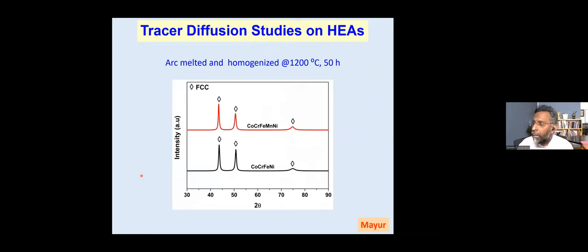The second aspect is, if I have these many elements sitting inside the unit cell, how do they diffuse? How do they move? Can I find out the diffusivities of these elements? Because diffusivities are useful to know when you want to find out whether the microstructure of some phase or some alloy is stable at high temperatures or not. The thermal stability is to a large extent related to diffusion. If the diffusivity is very low, the structures are very stable. If the diffusivity is high, then you can say that there is a tendency for structural changes to happen.